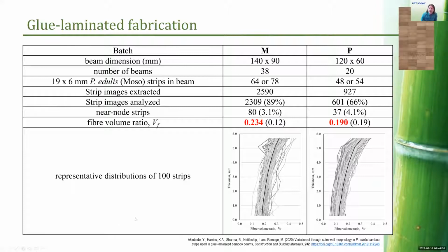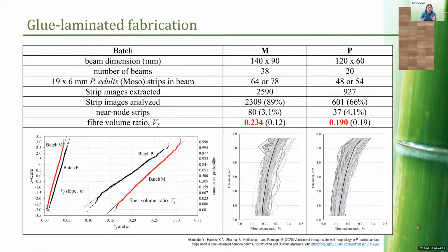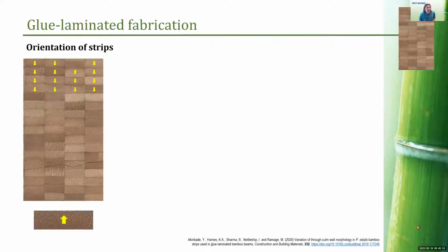And what was interesting immediately is that we see that between the 2 products, which are nominally similar, we have very different properties of the strips. The average fiber volume ratio is about 24% in the one case and about 19% in the other. Also a little bit more variation in this one, a little bit messier. One of the things that's important when we're thinking about these things is what distributions do they follow? And so we also wanted to make sure that when we're looking at something and we're going to talk about random distributions and how this behaves in situ, that it is in fact normally distributed, and it is.